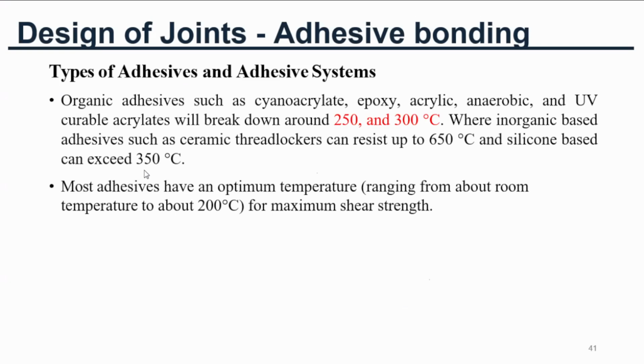Adhesives such as cyanoacrylate, epoxy, acrylic, anaerobic, and UV curable acrylates generally begin to break down at temperatures between 250 Celsius and 300 Celsius.